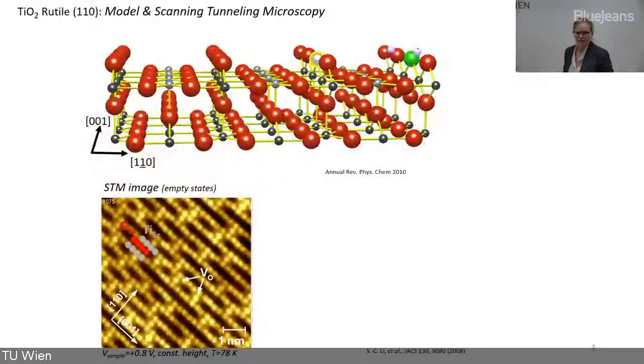I want to show a very early work. This is one of my favorite surfaces in life, the titania rutile 110 surface. On top you see a ball and stick model. You can see titanium atoms, the gray atoms, and the oxygen atoms, which are under-coordinated and stick out a little bit. On the lower side, you can see an empty-state STM image where each of these titanium atoms is very clearly visible.